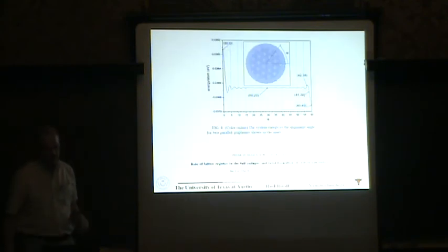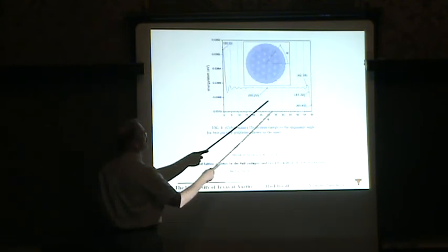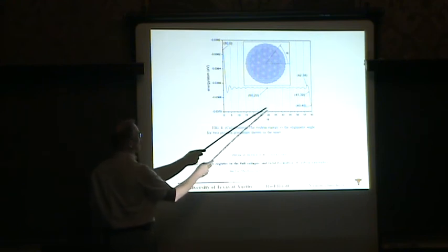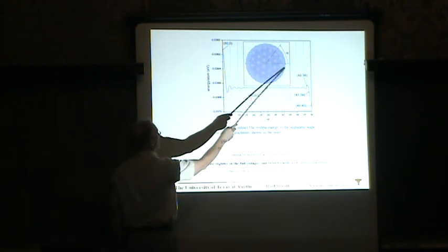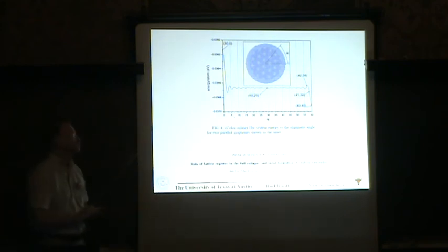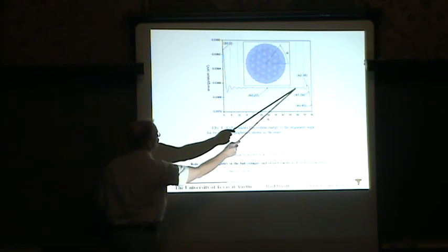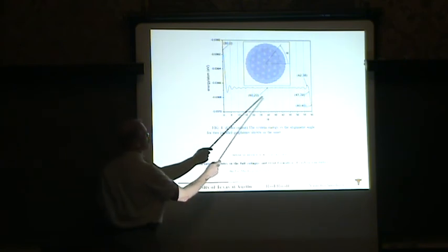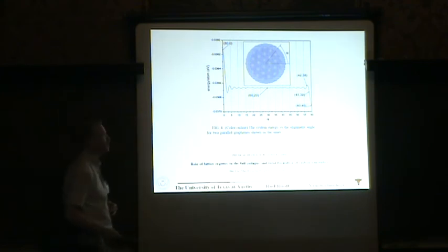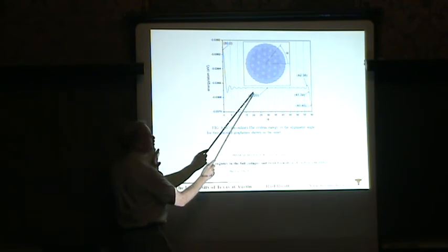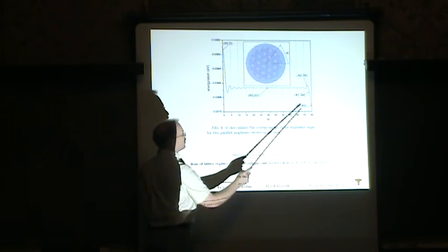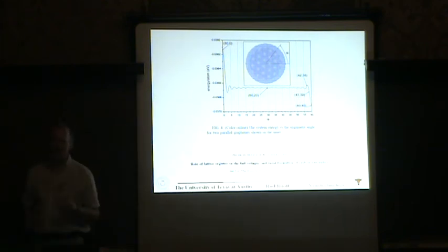They then developed this sort of color-coded mapping in terms of this angle alpha for rationalizing what the interlayer registry was, and therefore the driving force for twisting. You can see that even though a large number of the tubes are not stable to twisting compared to the armchair energy, there's a significant distance that they have to go to get over the barrier, so they may not twist significantly as a result.